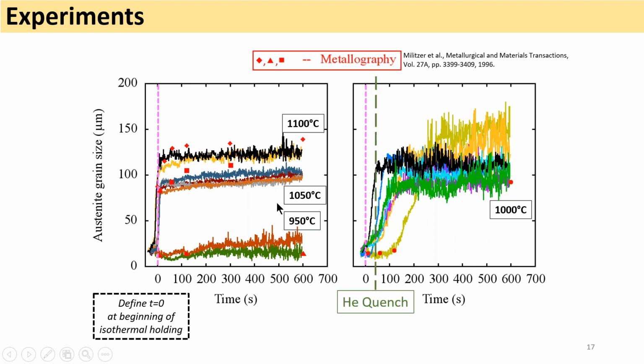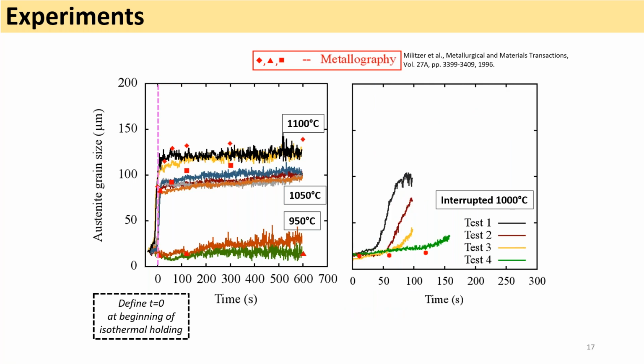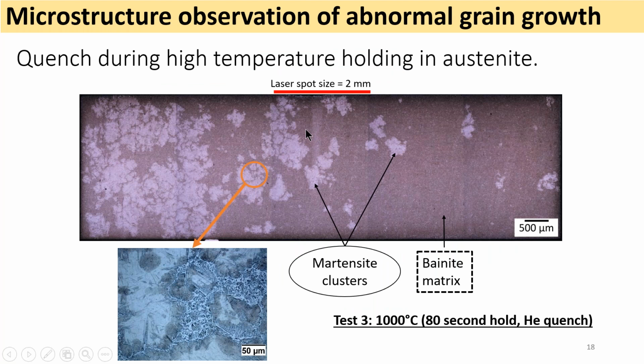I will show you here what we can see in the microstructure after quenching the sample. These are tests that we can do. If we quench the sample, we can visualize the microstructure and observe that there are patches of martensite in the sample, and those martensite patches are a sign that the grain size of austenite in this zone was much larger than the grain size in those zones here where we have more of a bainite matrix. The reason why it's martensite is that as the grain size of austenite is increased, the austenite decomposition will occur at much lower temperature, forming martensite instead of bainite.